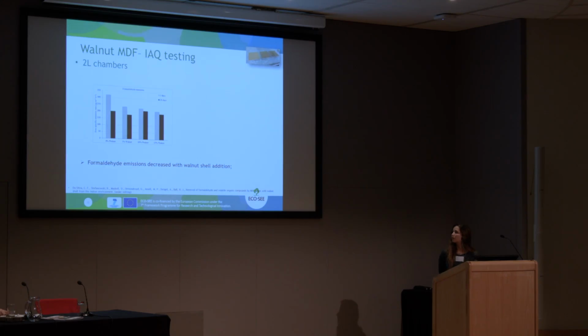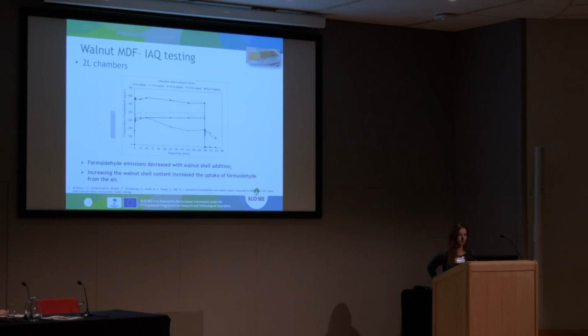So we confirmed that by increasing the content of walnut shell, the emissions of formaldehyde decreased, and we also did the adsorption-desorption of formaldehyde on these materials, and we observed that materials with a higher amount of walnut adsorb more formaldehyde and desorb less. So with this material, we can improve the indoor air quality.